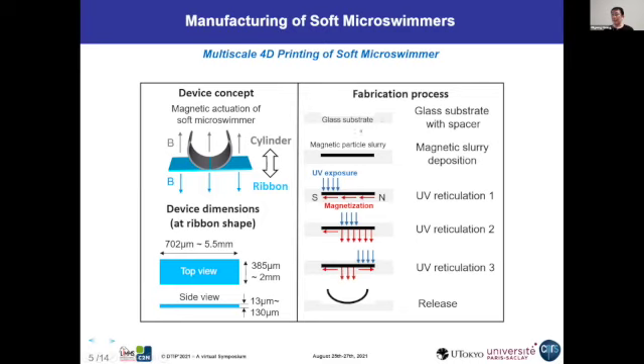For example, here in the case with the self-deforming cylindrical structures, we can magnetize in 3 compartments: the left side, the middle part, and the right side. So the UV reticulation is done sequentially on these 3 compartments. First, we globally magnetize the magnetic slurry from the left side, and then we locally UV expose the first third.